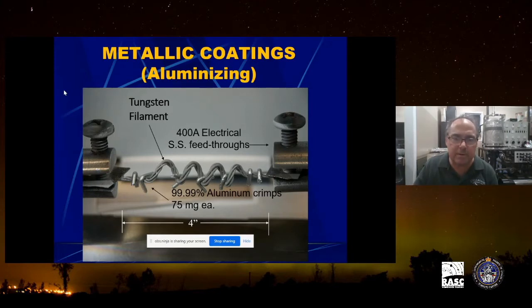You don't want to go too thick, otherwise the aluminum starts losing its luster and it'll look like a white piece of paper if the coatings are too thick. And if the coatings are too thin, then you can see light through them. So there's a happy balance there. Basically, we put a coating of 60 nanometers or so on there, and that makes it nicely opaque.